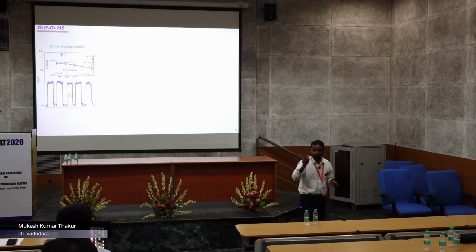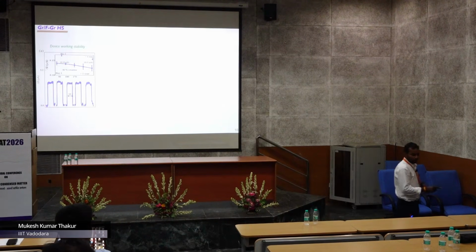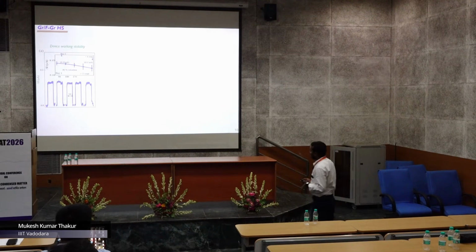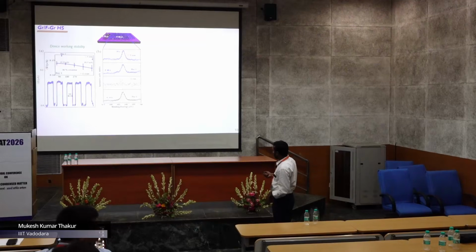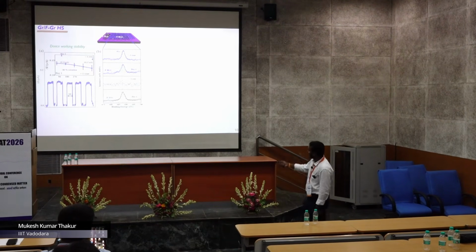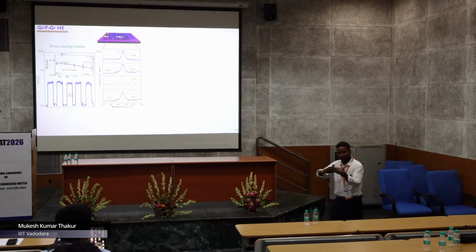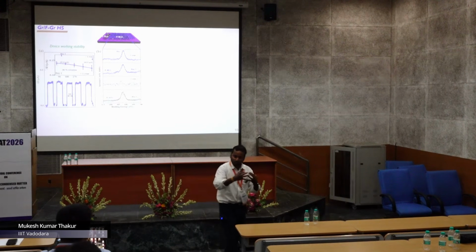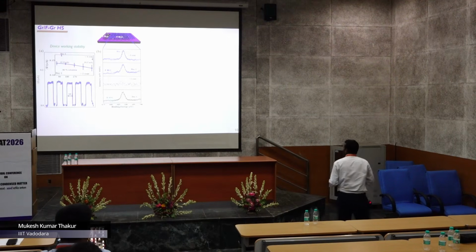Another question was: is the fluorine still there or not? How to confirm? Do XPS, very easy. Also Raman, but XPS is more elemental. If you see day 1, we have very nice fluorine in the fluorinated single layer graphene. After 1 year, this fluorine is gone. But with the heterostructure, on day 1 and after 1 year, the fluorine is still there. So basically this top layer in the heterostructure also prevents fluorine migration. They have an interaction, and they don't allow it to go away.